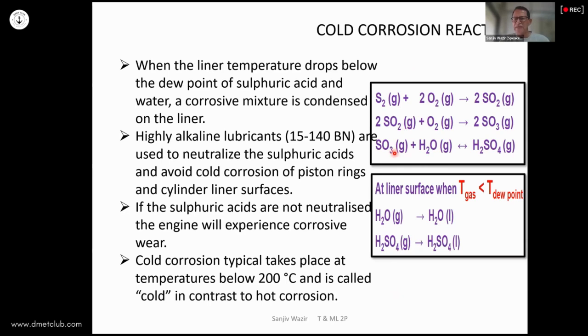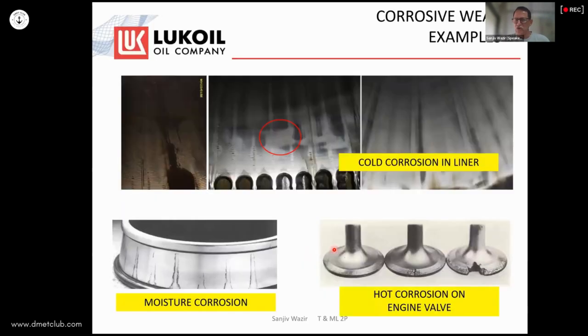So long as it remained gases and left with the exhaust, we wouldn't really bother. But once water is formed and this is formed, and then the temperatures of the surface are suitable enough for this, now as liquid acid, to start depositing on the liners, then we used to have this problem of cold corrosion. And that's why all our cylinder oils used to be so alkaline. Currently, the alkalinity of cylinder oils is in this range, 15 to 140 BN. So depending on the nature of the wear, nature of the machinery, nature of the sulfur content, the BN of the oil we used. So you're familiar with this cold corrosion that had become very common in the earlier era before VLSFO.